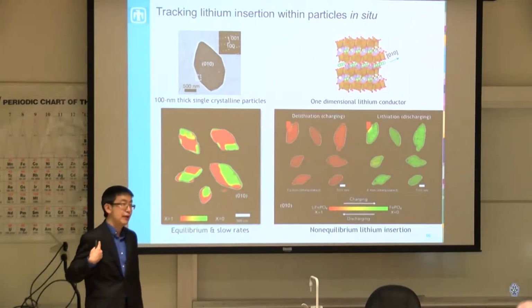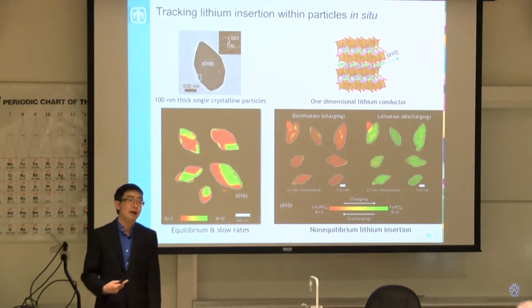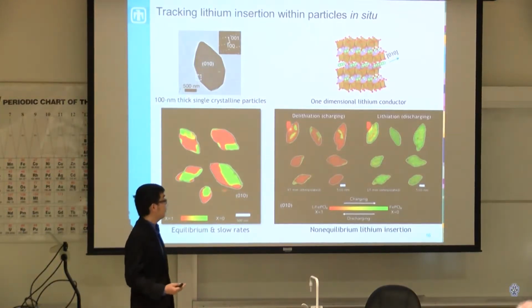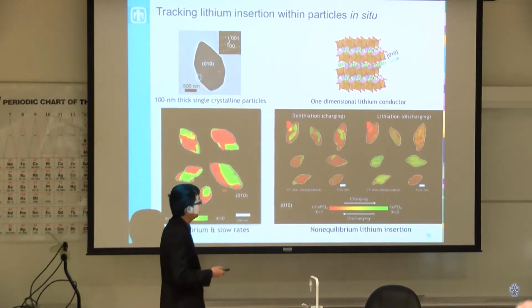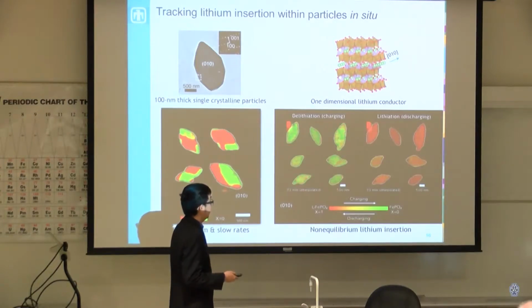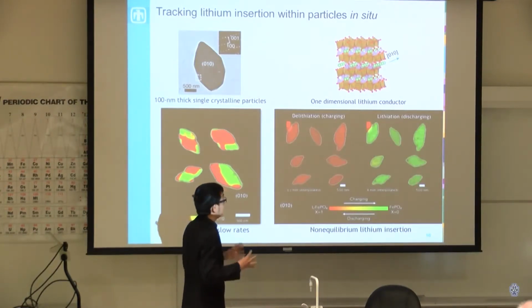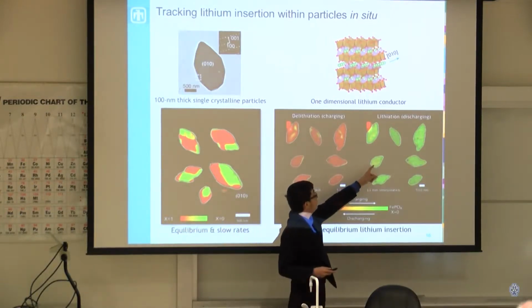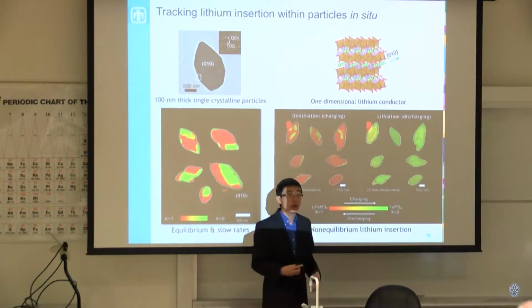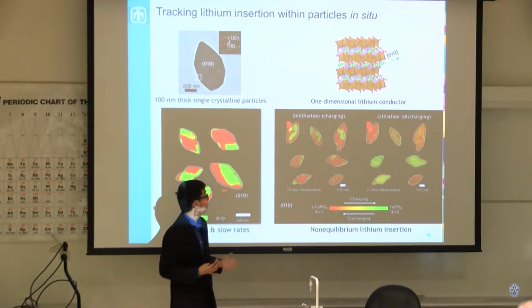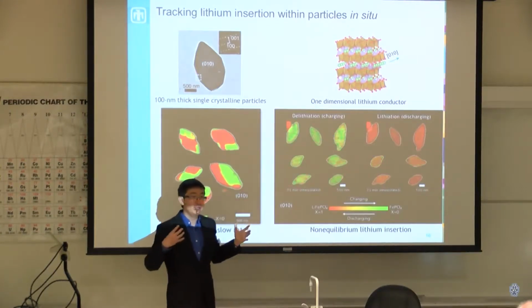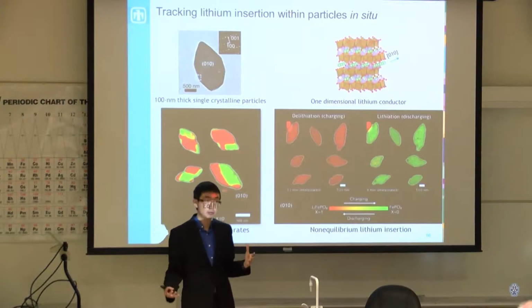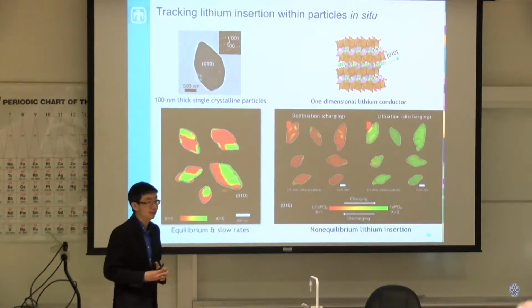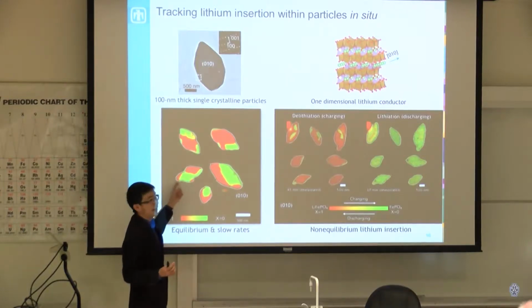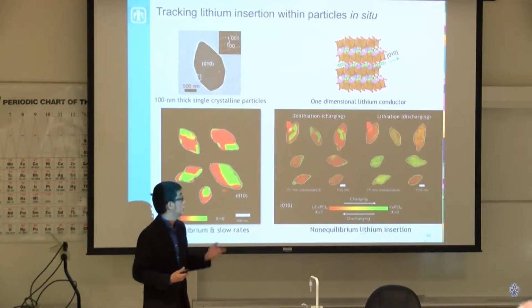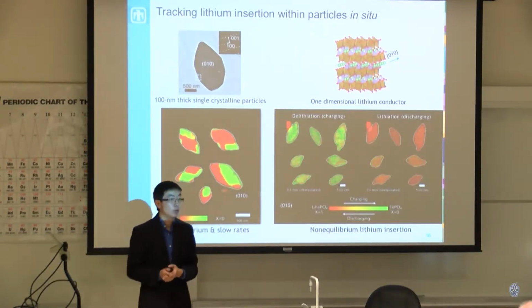However, if we try to image live batteries, if we try to understand what happens in the battery while it is being charged and discharged, we see a very different picture start to emerge. I want to point your attention especially to the pictures on the right. It's going to restart again, playing a loop. And then what we can see is that we don't see these clear phase boundaries. What we see is that lithium inserts fairly uniformly into these particles. So instead of seeing an agglomeration of red and green with these sharp phase boundaries as we do here, we see it go from green to yellow to orange to red. So we get a much more uniform intercalation of lithium. Whereas if you take a dead battery, you might see something like this, when you do a live battery, we see a very different feature start to emerge, in that phase separation is suppressed when you charge this battery quickly.